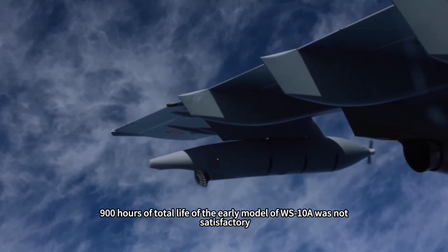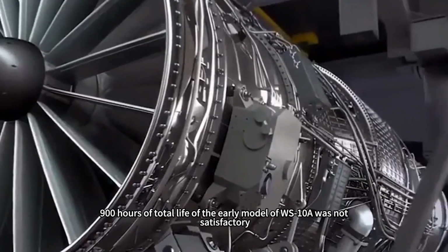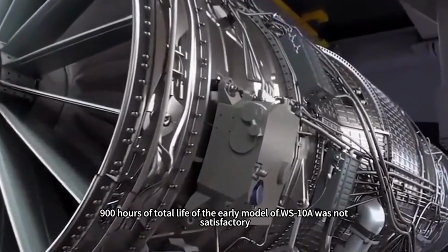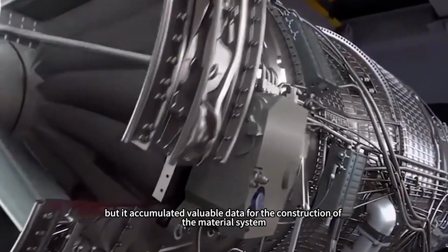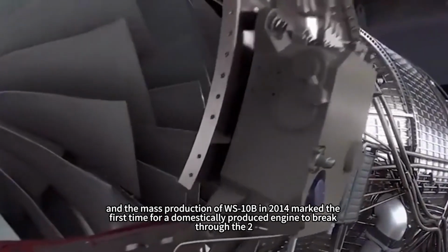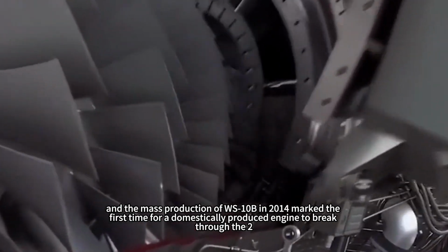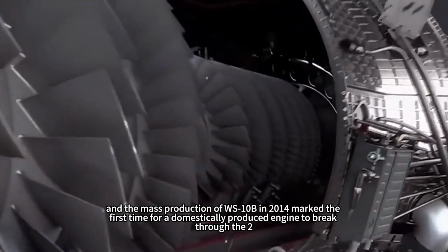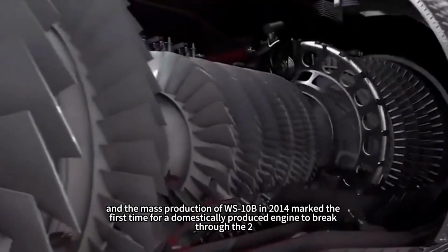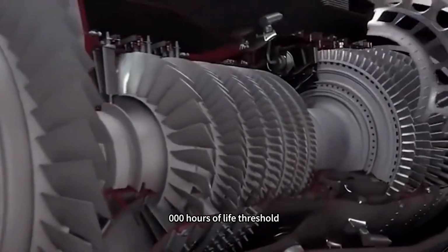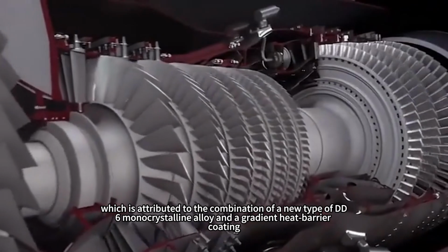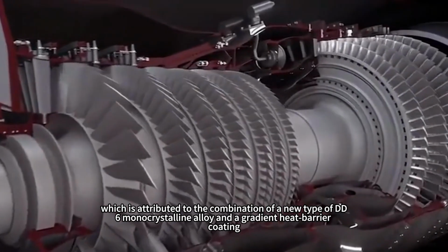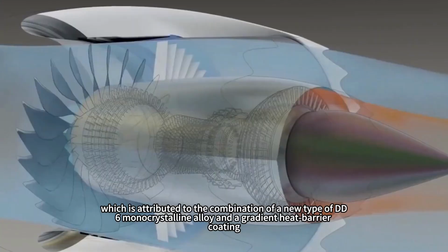The breakthrough path of China's aircraft engine industry shows a unique, iterative leap characteristic. The 900 hours of total life of the early model of the WS-10A was not satisfactory, but it accumulated valuable data for the construction of the material system. And the mass production of the WS-10B in 2014 marked the first time for a domestically produced engine to break through the 2,000-hour life threshold, which is attributed to the combination of a new type of DD6 monocrystalline alloy and a gradient heat barrier coating.